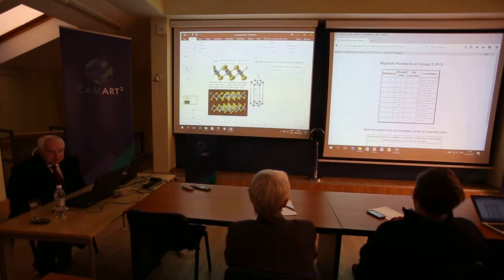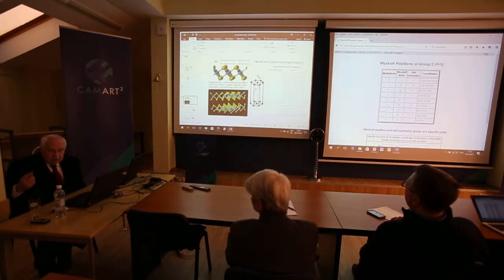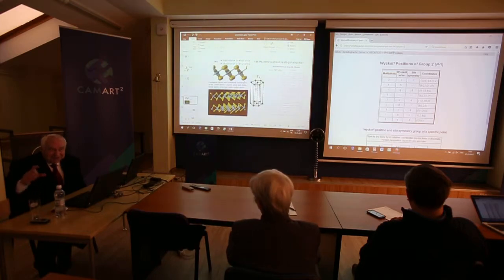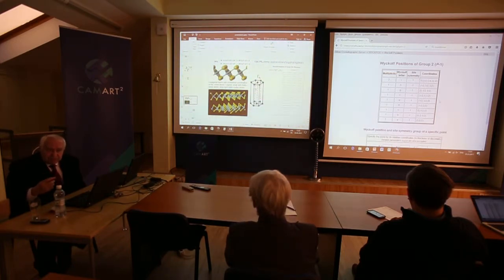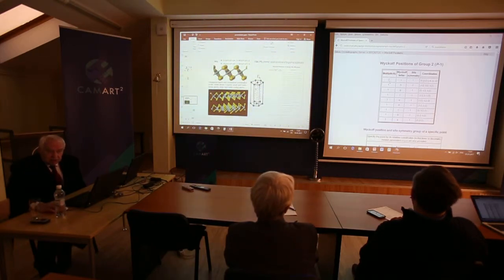Because, very simple. Minus 1, this is simple inversion. If you take 0, 0, half, then minus 1 gives you 0, 0, minus half. But half and minus half are connected by a translation vector. And the same with any number of halves in the coordinates. So these Wyckoff positions are not equivalent, but each of them consists of 1 point. But why here 2?